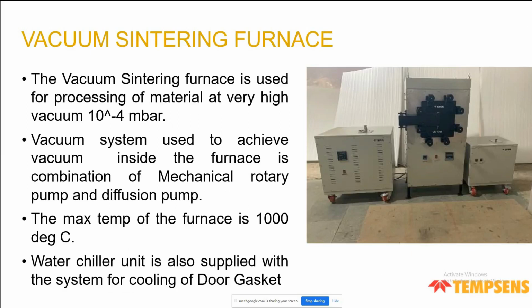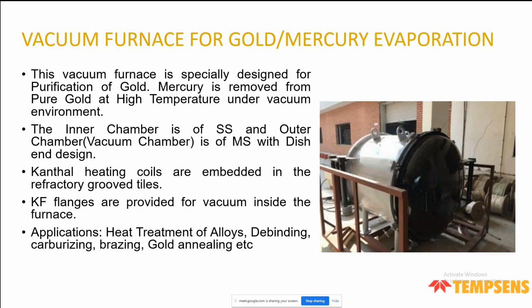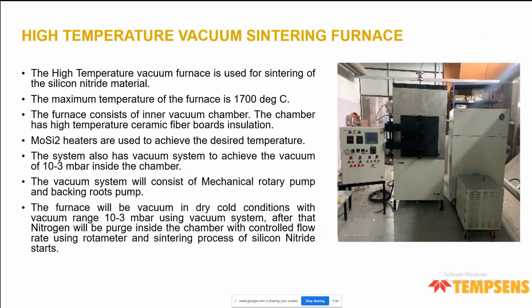So this is a vacuum sintering furnace with 10 power -4 millibar vacuum, and temperature up to 1000 degrees centigrade. So this was for a customer in South Africa. We supplied this furnace for purification of gold. So this is again a vacuum furnace, and they wanted to remove the mercury from the gold. So I think it was going up to 1200 degrees centigrade or so, and this was supplied about, I think, 2-3 years back, and I hope the customer is using it fine, because we did not hear anything from them, and he wants some additional heaters now. This is just now supplied to, I think, DRDO